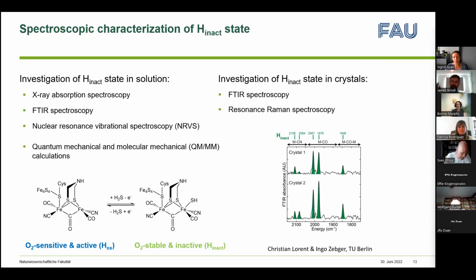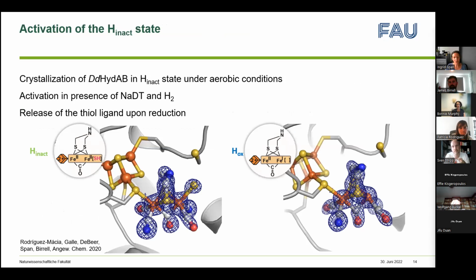So this was our first goal, to characterize the mechanism of inactivation. And now we're also interested if we can reactivate the state, and in particular, if we can reactivate the state in the crystal structure. So crystals consist of 40 to 60% water, so they are quite flexible. So I already learned in my PhD that chemical reactions can occur inside a crystal. So what we did, we crystallized the enzyme in the H inact state under aerobic condition, and then we tried to activate it in the presence of sodium dithionite, a reductant, and hydrogen gas. So hydrogen gas approximately 2%, because this is in our glove box.